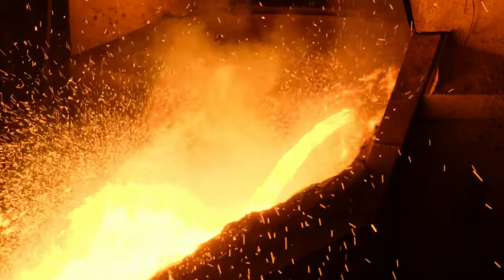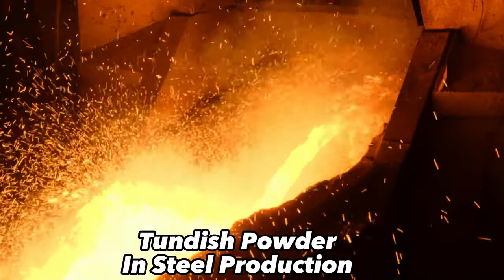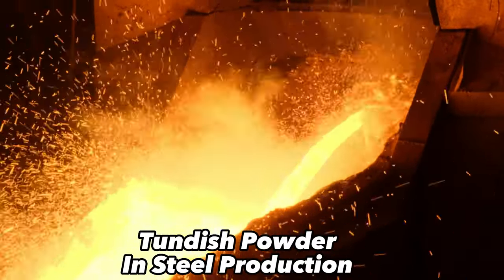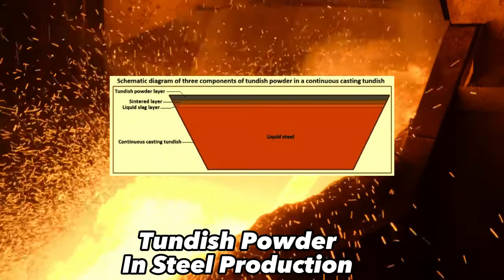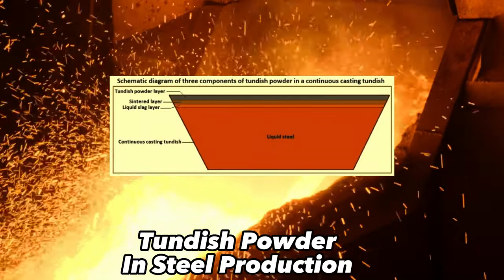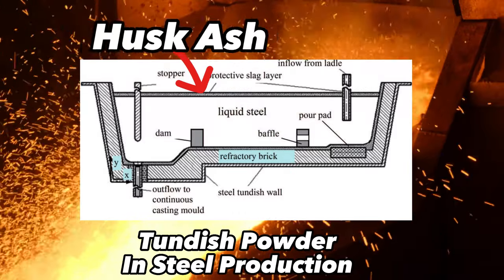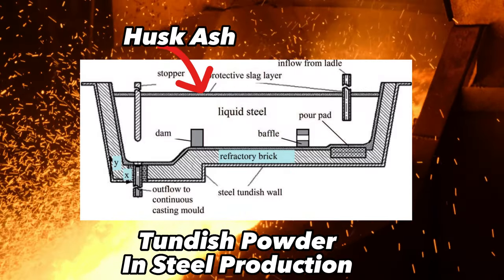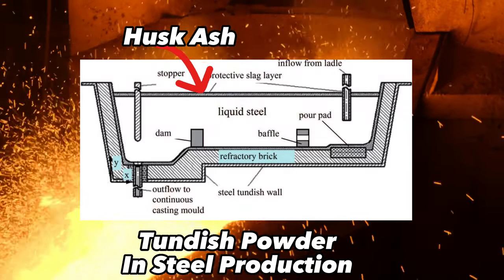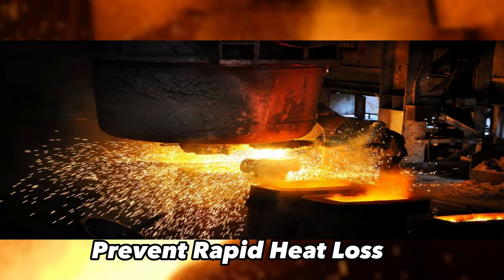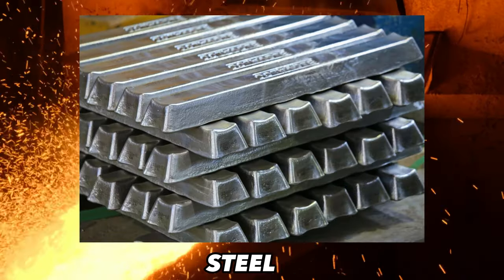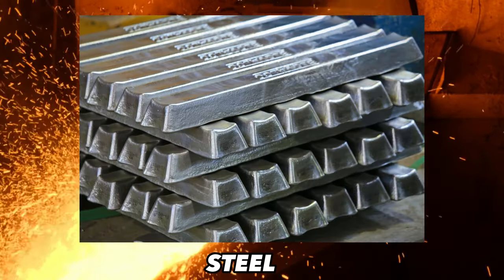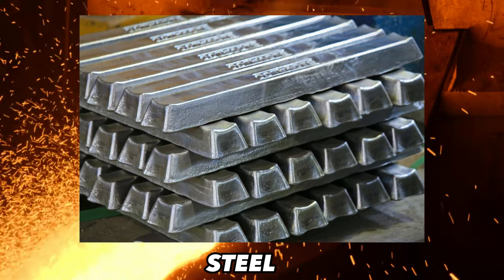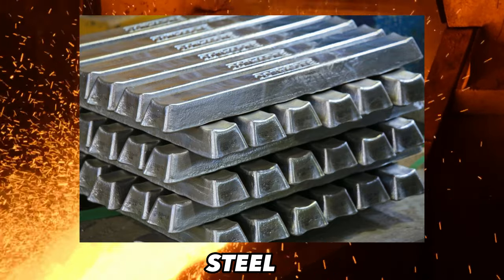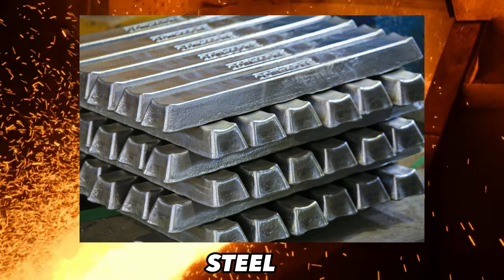Rice husk ash has been used as a tundish powder, which is a low-value product in steel production. The tundish is the vessel where molten steel is filled. Husk ash is thrown on top of the tundish after it is filled with molten metal. The role of husk ash as tundish powder is to prevent rapid heat loss from the steel surface and reoxidation of the steel. These qualities make husk ash an excellent insulator to prevent the rapid cooling of steel and to ensure uniform solidification during the continuous casting process of steel.